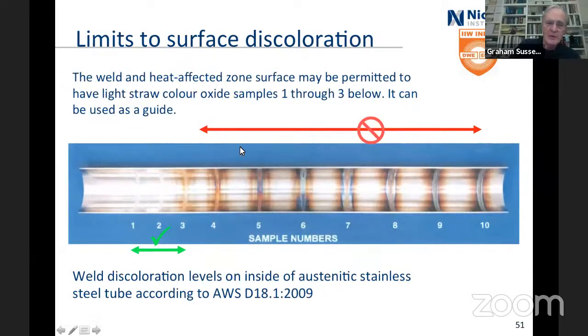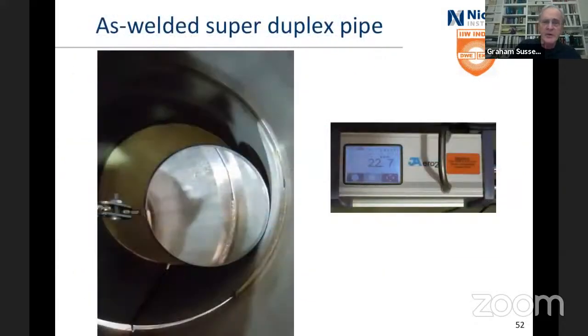Surface coloration, much the same as for austenitics, 50 parts per million oxygen, light straw color, and that's what's set by AWS D18.1 2009. Actually, there's a later version of that now, which I'm having trouble downloading. But it's levels 1 to 3, and everybody agrees on that, and the Sandvik people and others did a lot of work showing that while that was done for hygienic purposes, for corrosion purposes, it's also a good number. And you can do it. This is hand welding of a super duplex piece of pipe with 22.7 parts per million of oxygen, and it's a good, clean weld.